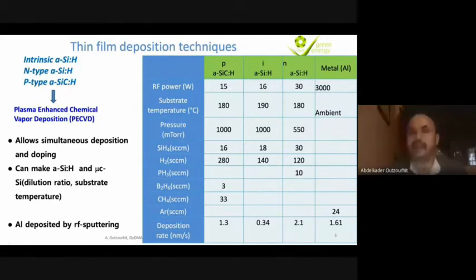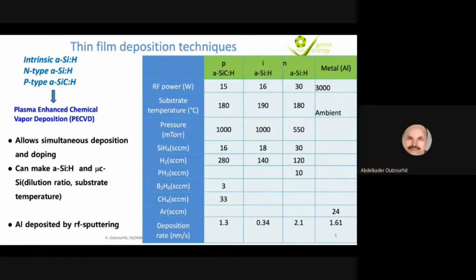As you can see, aluminum is deposited by RF sputtering under an argon atmosphere at a power of about 3,000 watts. For the other films, the plasma power is about 15 to 30 watts, which is rather small power. In addition, the deposition temperature, or the substrate temperature, is rather low also. It's on the order of 180 to 190 degrees C.